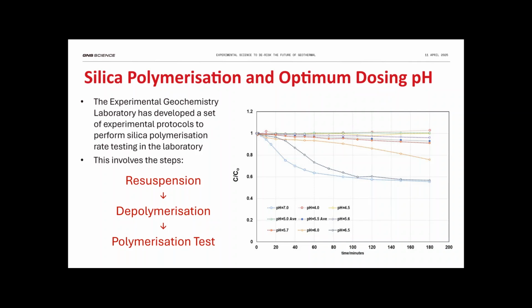We can also do something that cannot be done in the field, which is we can do silica polymerization testing at temperatures above 100 degrees. So we actually have stirred pressure vessels whereby the brine is heated up past amorphous silica saturation to depolymerize the silica, and then it's cooled down to the reinjection or the dosing temperature in the same pressure vessel, and then we can actually sample over time the brine and measure the polymerization rate at temperatures above 100 degrees, which is something you cannot do in the field.